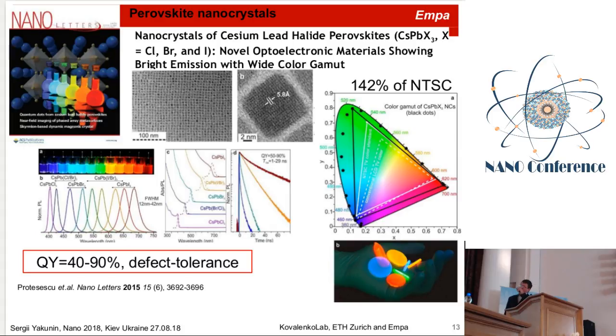And then it's already our work. As I mentioned, we started to cook by hot injection colloidal chemistry pretty nice, cubically shaped due to the cubic crystallographic structure, and very monodisperse perovskite nanocrystals, and they are quite unique in properties. So first of all, they have very high optical absorbance, reaching values of about 10 to the power 5 inverse centimeters, which is pretty high. And then they have very narrow optical emission with very high quantum yield, reaching almost 90% quantum efficiency. And this narrow emission can also be tuned continuously through the whole visible range.